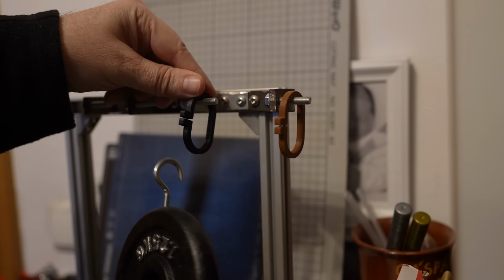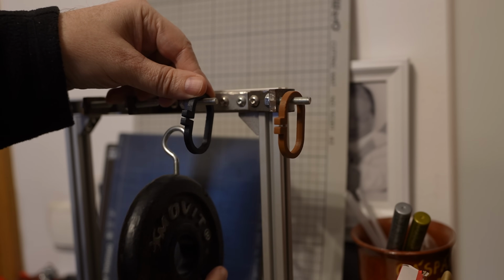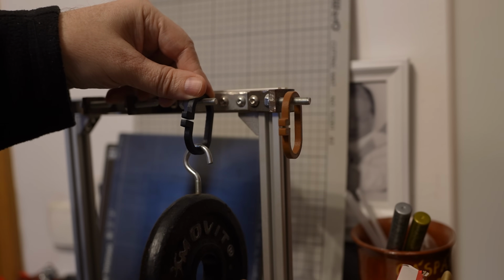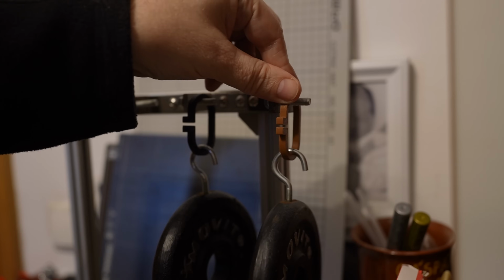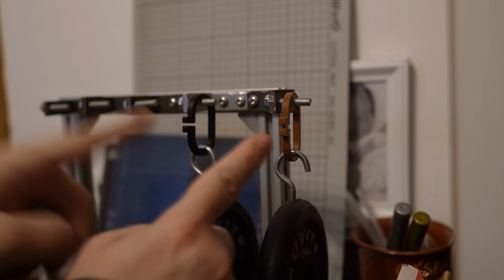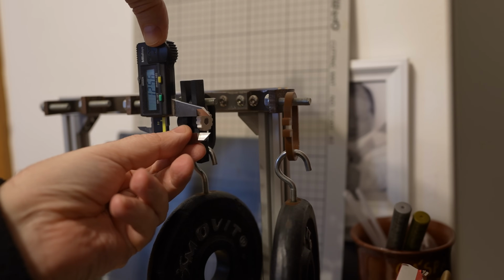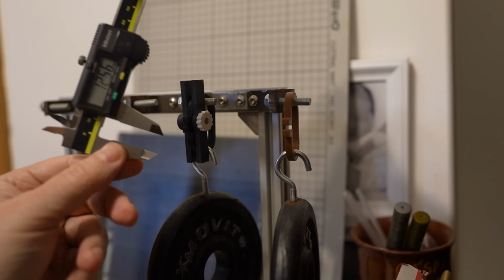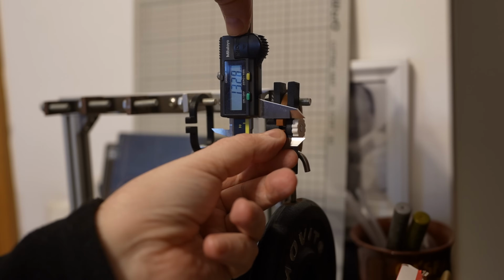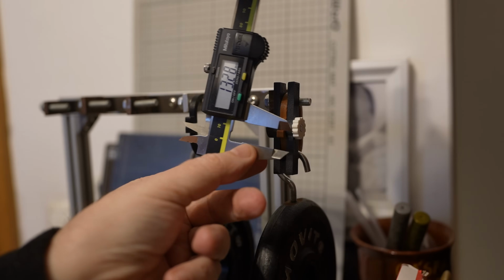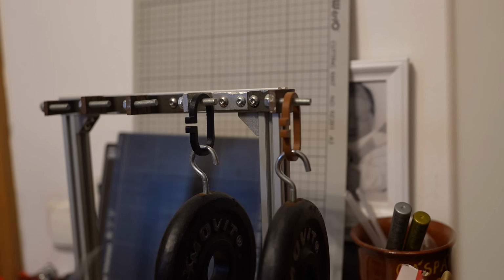The creep test, the deformation under the constant load of 1.25 kg. Very minimal deformation. 12.56. 13.28. A little bit more deformation on the glass fiber version, but both are very stiff materials, and now we measure them every day and we will see how much creeping we will have after 5 days.